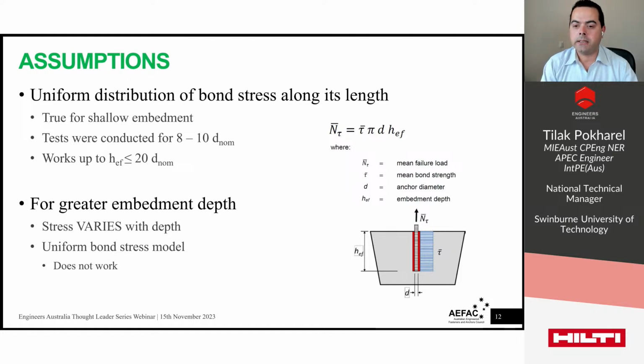It has been tested extensively in Australia and in Europe and other countries for 8 to 10 times the diameter of the anchor. And it has been proved to work well if the embedment depth is about 20 times the diameter of the anchor. And this is the reason why there is a limit in the maximum embedment depth of the anchor in the anchor model. So as you expect, this uniform bond stress model does not apply to anchors with deep embedment in reinforcing bar applications. So we cannot use this anchor model from AS 5216 to calculate the pull-out capacity of the long post-installed rebar, which is more than 20 times the diameter of the anchor.